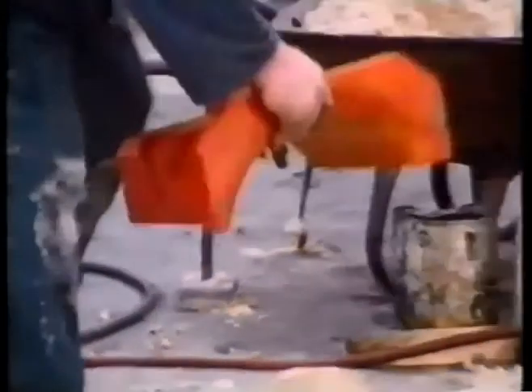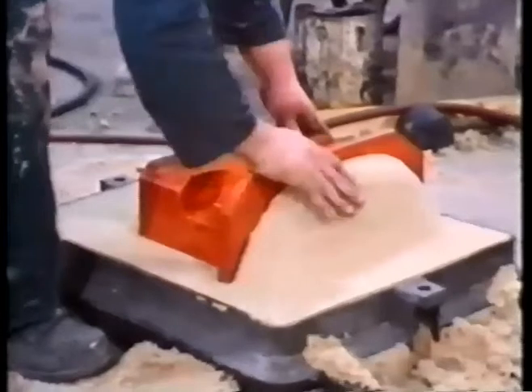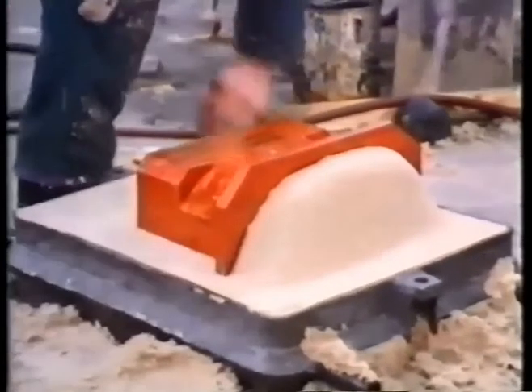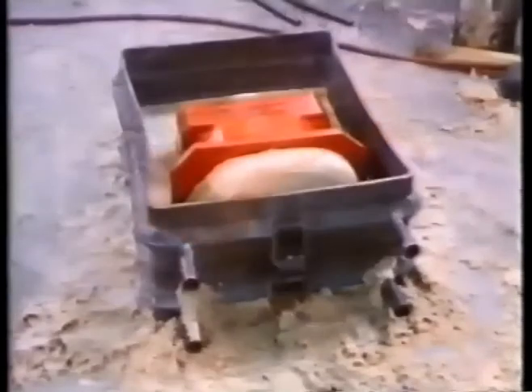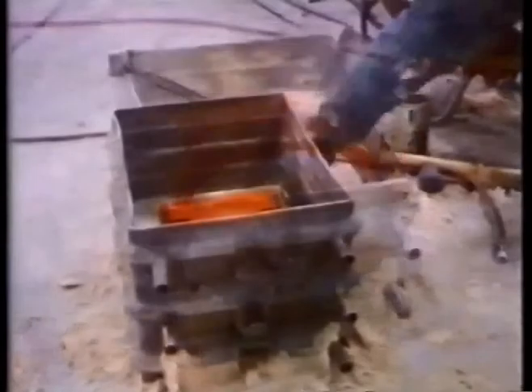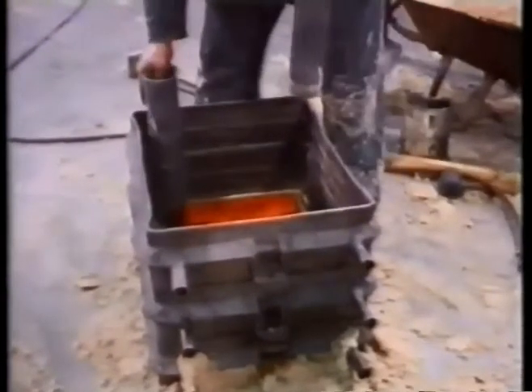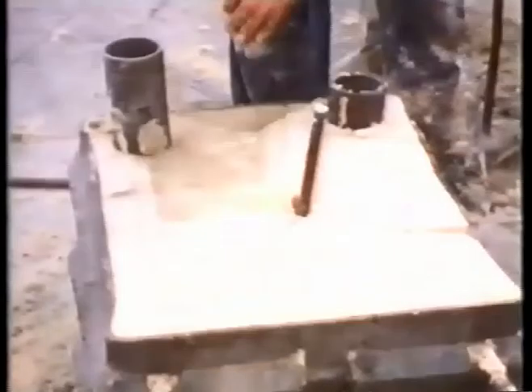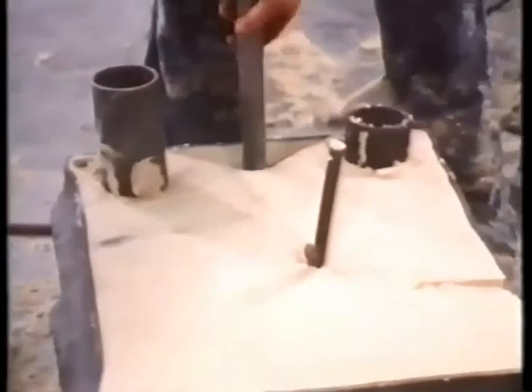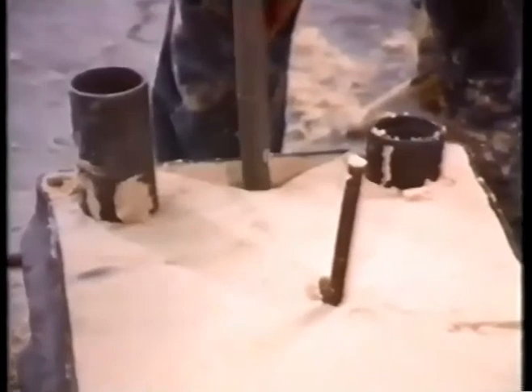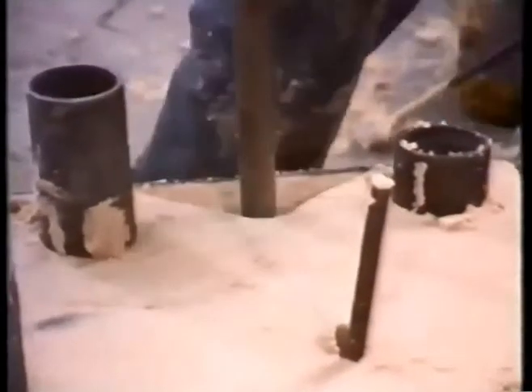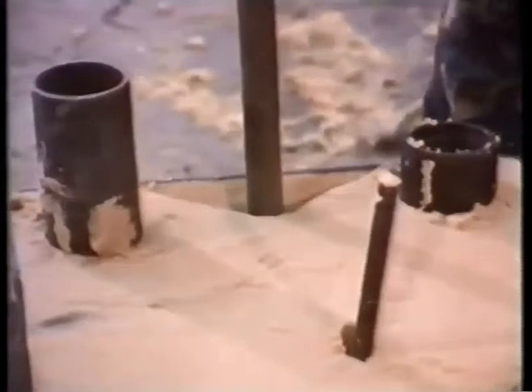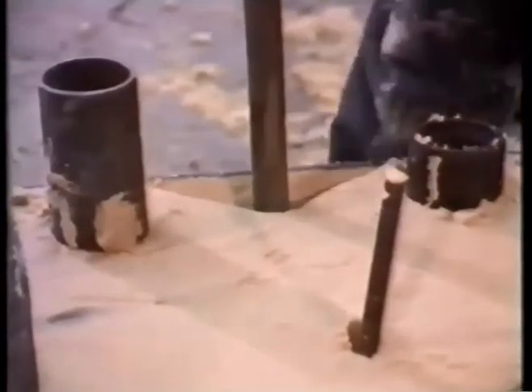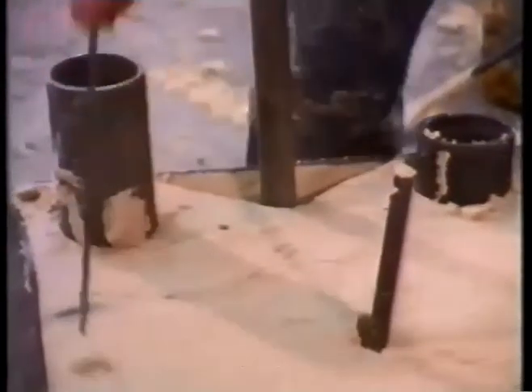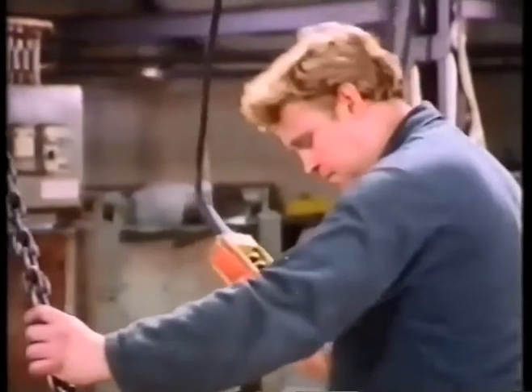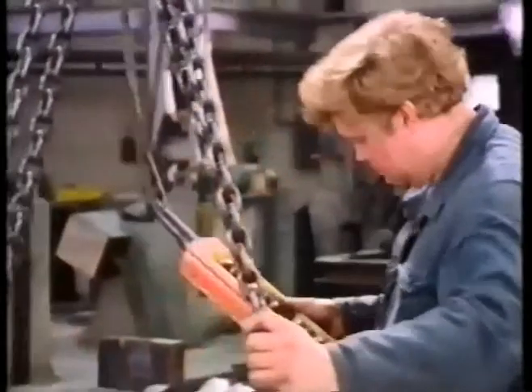The pattern is then put back onto the now hardened bottom half of the mould. Another moulding box is added, and the tubes to form the risers are put into position. The rest of the sand is added, and the feeder through which the molten metal will be poured is formed. The top is hardened with carbon dioxide gas, and the mould is now almost complete. It's then broken down again because the wooden pattern has to be removed.